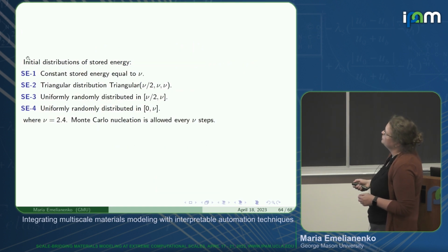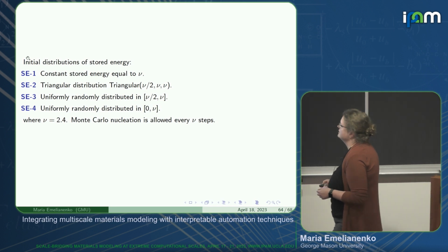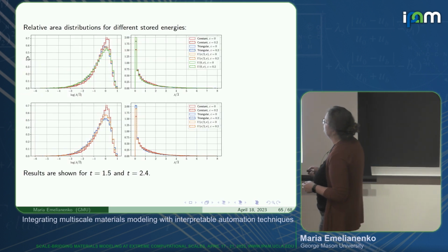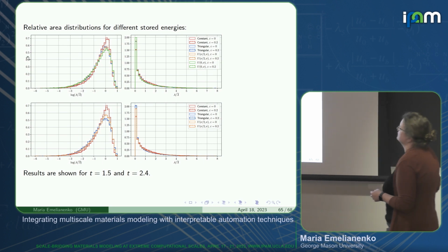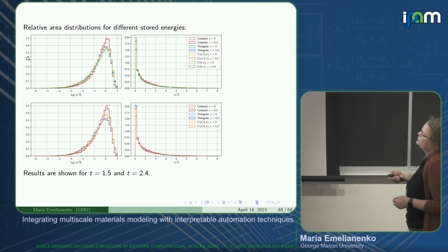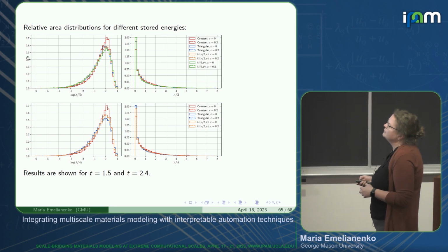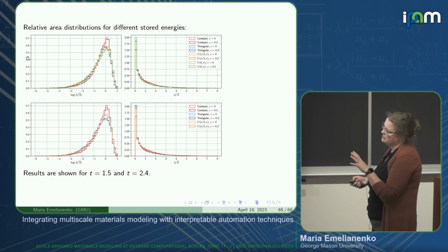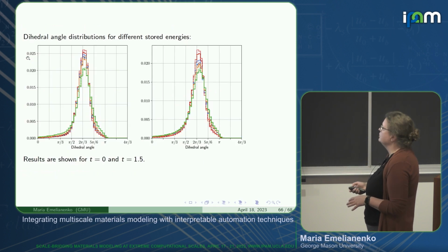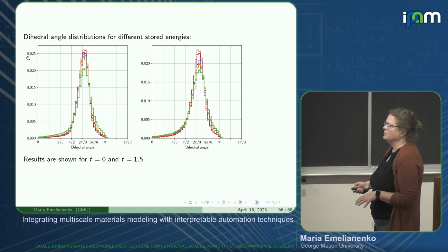We tried to distribute the stored energy in different forms and did the nucleation at a certain point and looked at the statistics. Similar to our previous results, we can see deviations. The general shape stays the same, but you can actually modify these distributions if you pick this nucleation regime in a certain way.